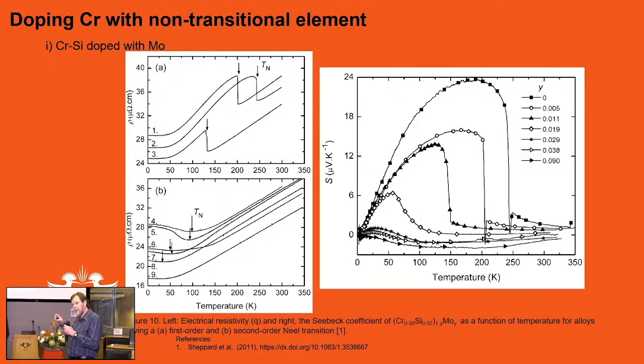We want to track a quantum criticality. What happens when this phase diagram approaches 0? It becomes very sharp. You'll see the data now. So in this case, we have first order. So the molybdenum has effectively a similar Fermi surface to chrome. So it should not affect the chrome magnetically in this case. But it affects it because it affects the interaction between the chrome. So then we can add more molybdenum and we have better control. But the trick is that now this phase boundary, this transition, changes from a sharp transition to a smooth one, going from first to second order.